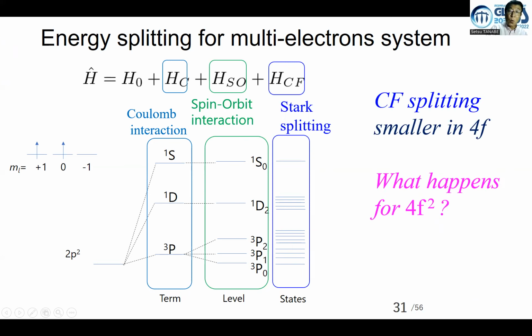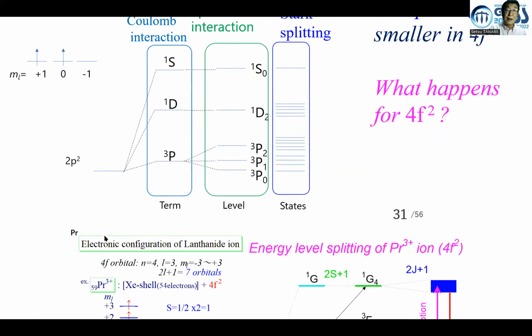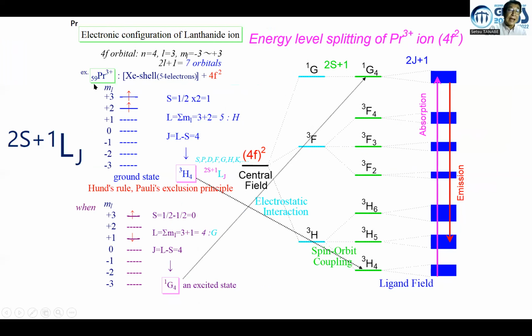So what happens for the 4f2 electronic configuration? This is like the p2 configuration, which is different. In the case of trivalent praseodymium 59, which has only 2 4f electrons, the total spin becomes 1, unity, so a triplet state. And the total angular momentum becomes 5, corresponding to the letter H. And the total quantum number J equal to L minus S is more stable, becoming 4. So this electronic state is expressed as triplet H4, which is the ground state of the trivalent praseodymium ion.